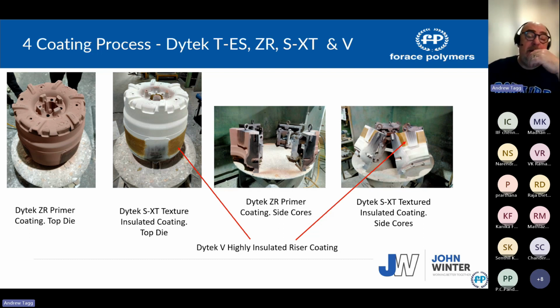But when you're making wheels with gravity die casting, the metal enters, I'll show a picture of the die, the metal enters through the center into the bottom and goes up the sides. To stop shrinkage, you have to feed it from the top, and the resultant effect of that is you need a heavy insulated coating to enable directional solidification back to the risers. Also, this is why in this application we're adding a riser coating, which helps promote directional solidification.